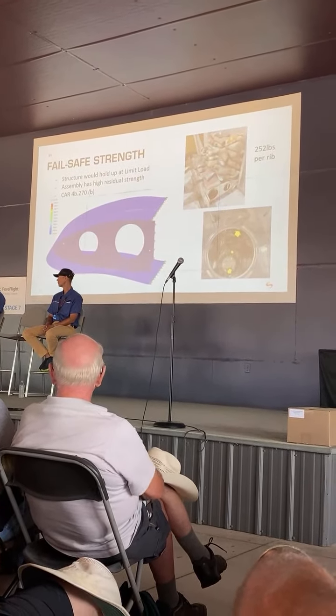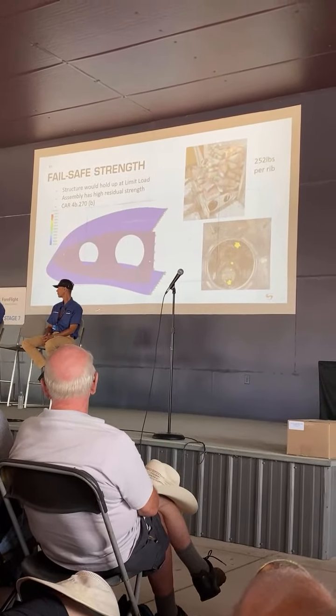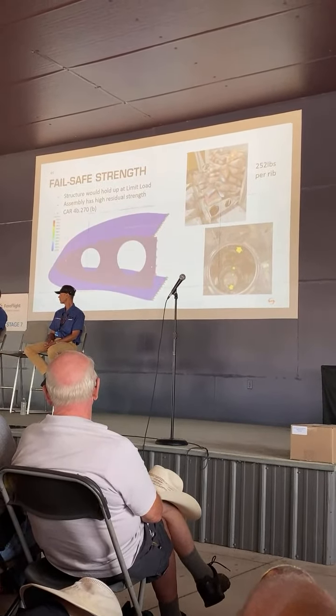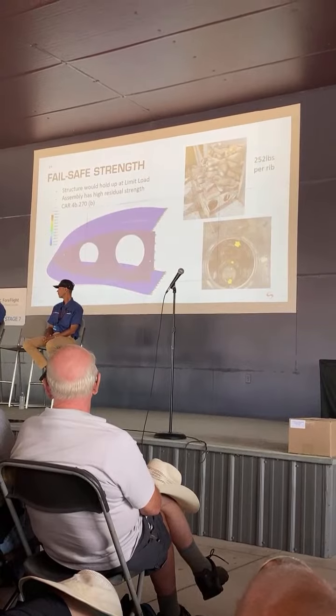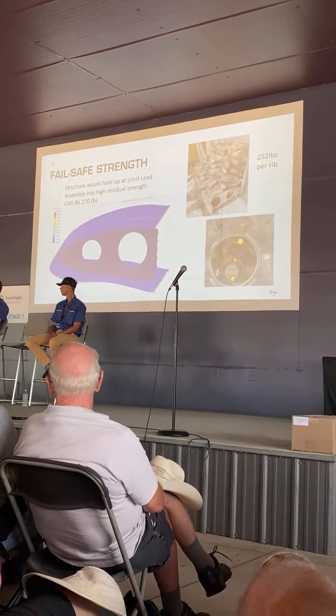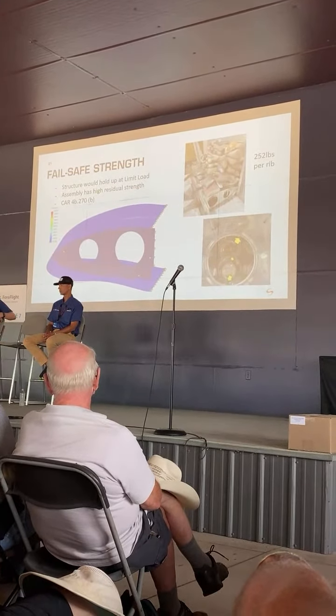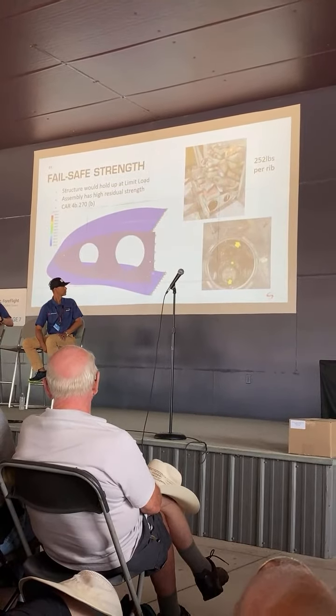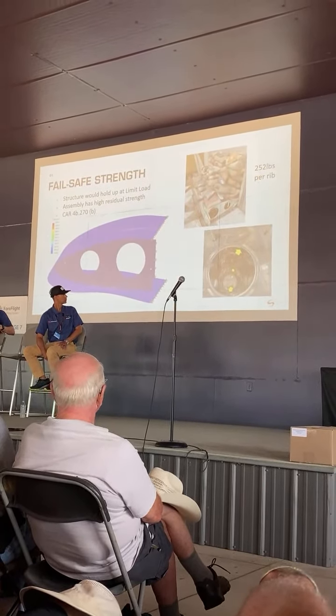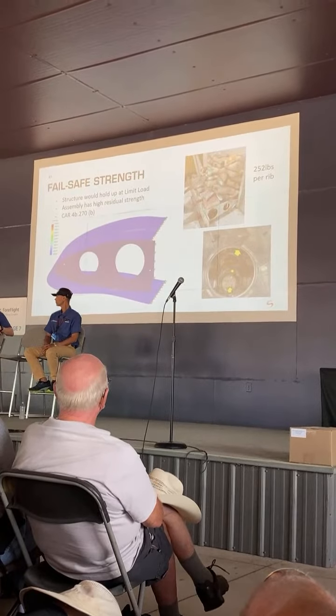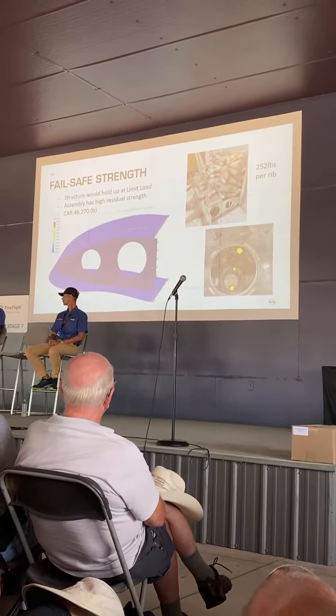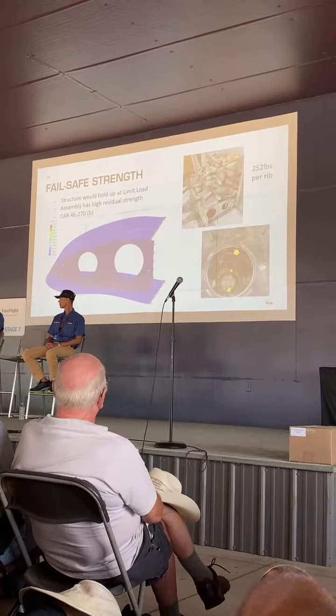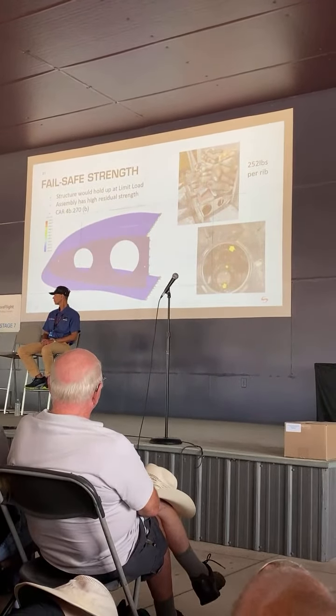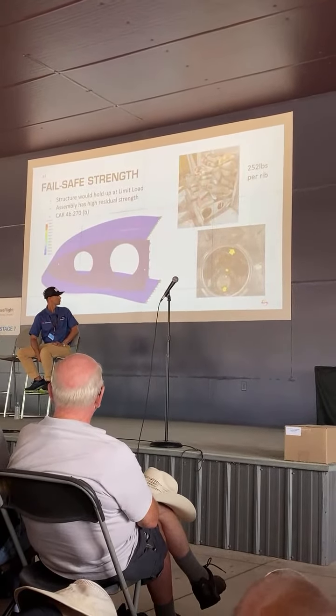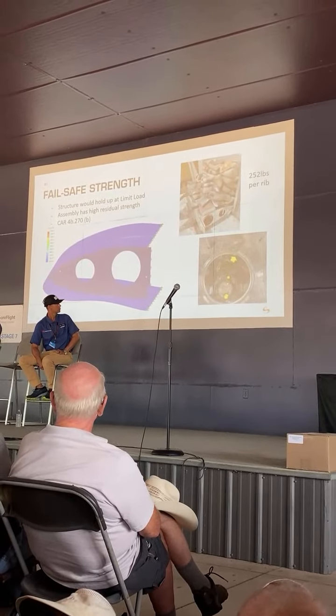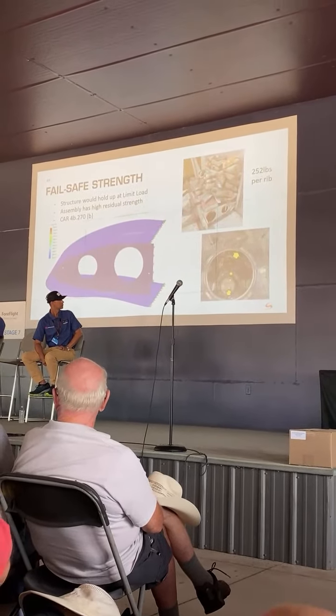Again, in this picture here, we're actually showing the crack forming from the notch itself, since it's highly likely that that would be the case. If the crack had formed at the rivet, it would have just chopped off the back of the rib, and there wouldn't be that much structural loss. So we failed that, and we cut across top and bottom, and then also in the front lightning hole, but that's not shown here, and then load up the part. We're doing this with a full wing currently.